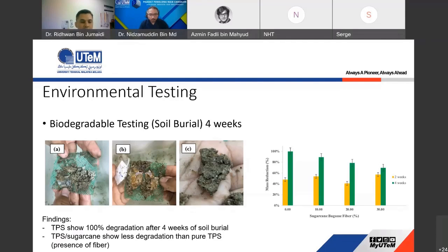And then what happened to the samples? Previously, the samples were rectangular in shape. After 4 weeks, all the samples have shown very rapid degradation. In fact, if you can see in this picture, there are some insects starting to eat the samples. So it shows how environmentally friendly the material is. And when we add the sugarcane fiber, some of the structure becomes a little bit stronger, and of course it slightly reduces the biodegradation rate. But nevertheless, all of the samples are still environmentally friendly.